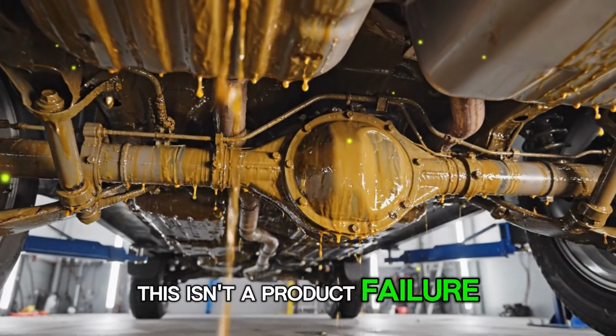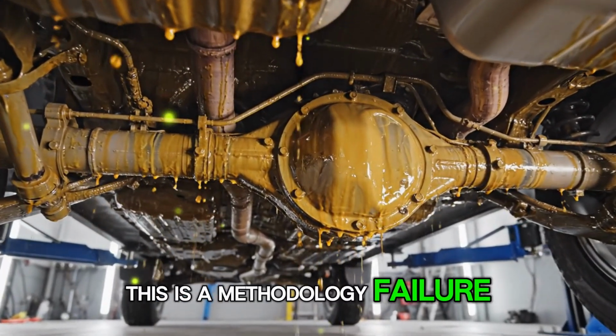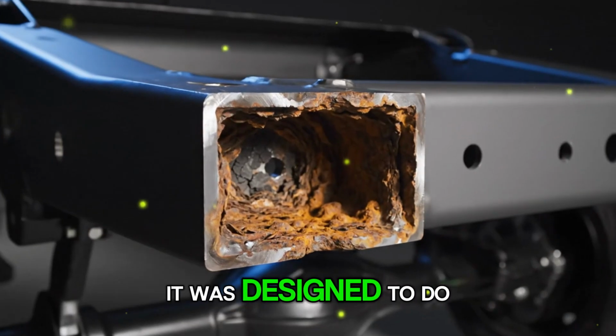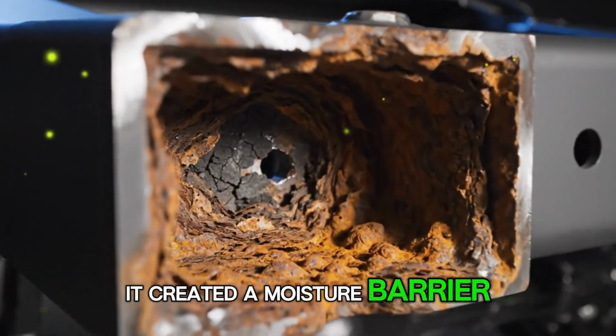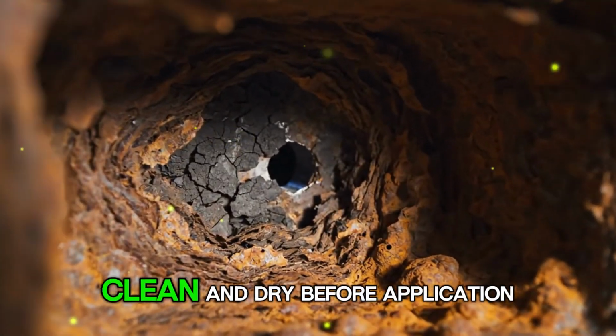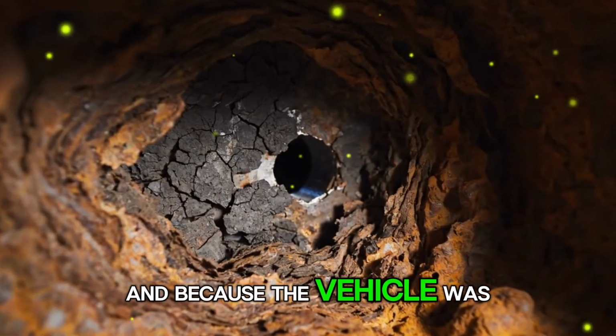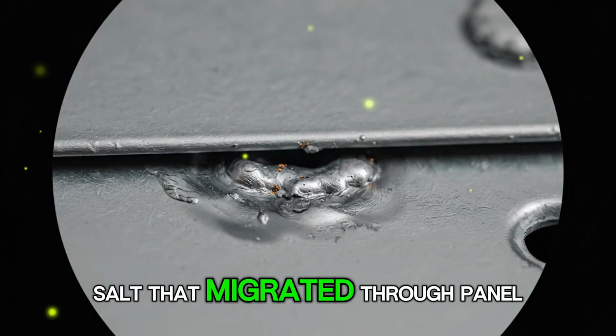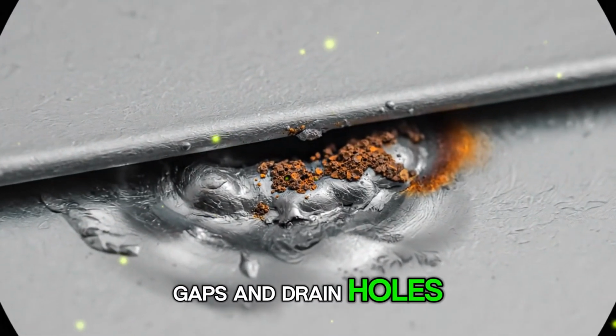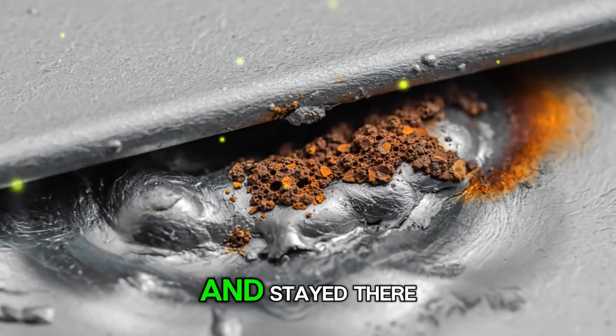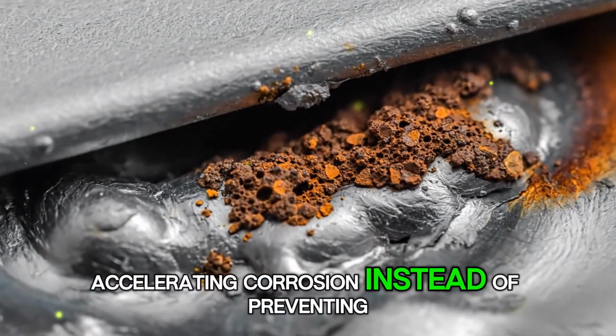This isn't a product failure. This is a methodology failure. The coating did exactly what it was designed to do. It created a moisture barrier, but because the surface wasn't clean and dry before application, and because the vehicle was exposed to road salt that migrated through panel gaps and drain holes, moisture accumulated behind the coating and stayed there, accelerating corrosion instead of preventing it.